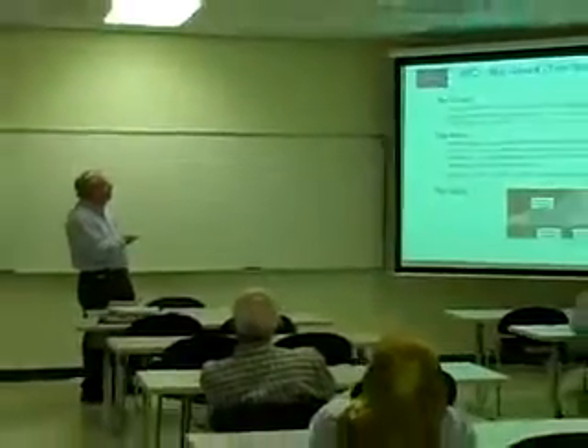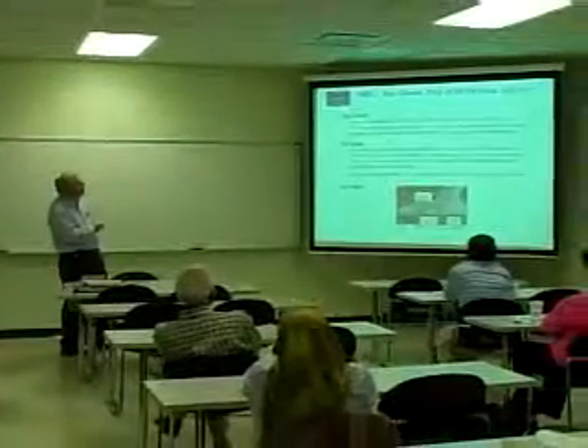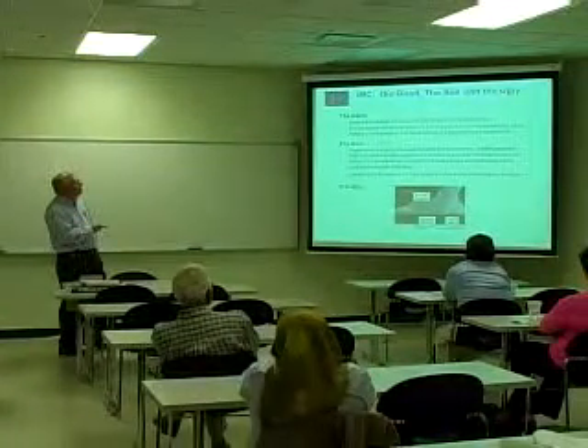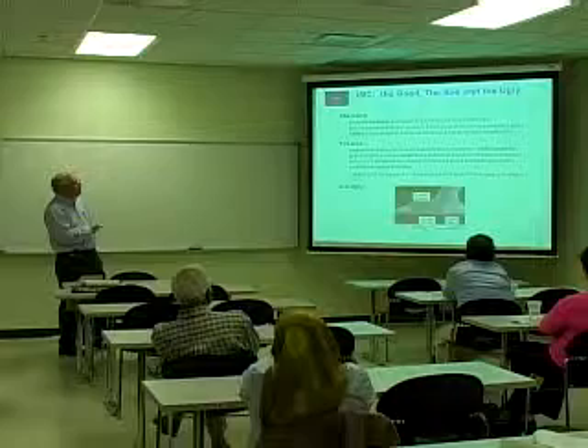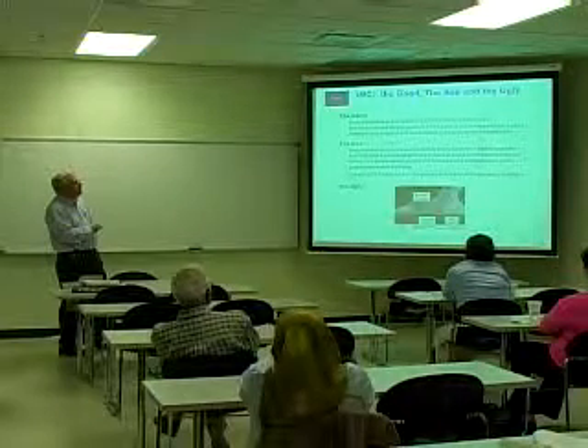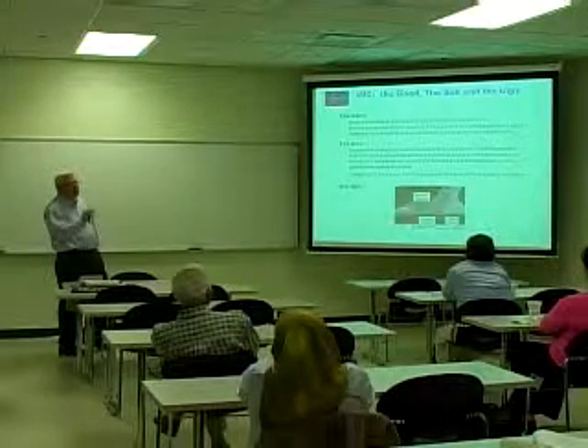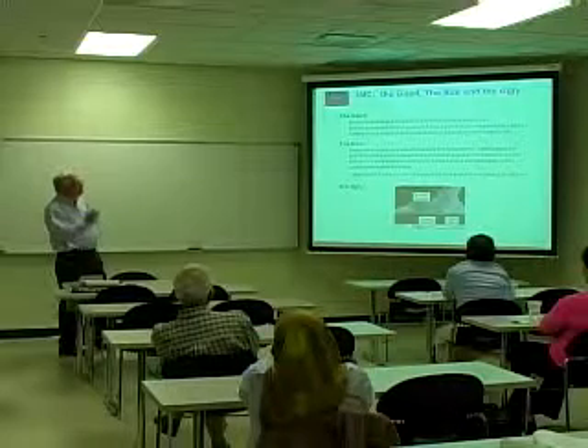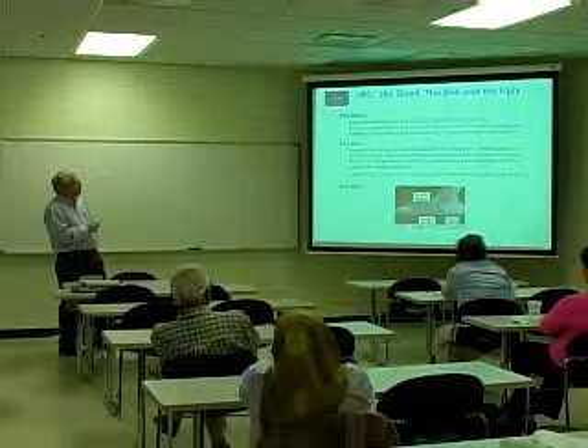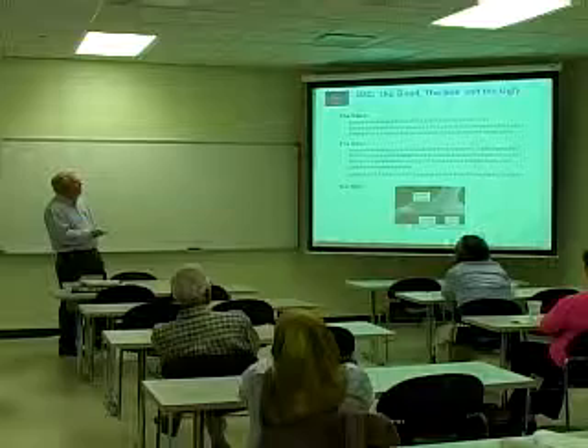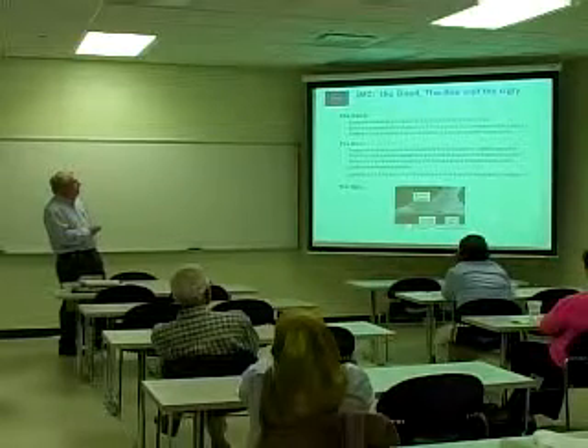And so what people do is they have to have some intermetallic formation. That's why I call this the good, the bad, and the ugly. You want some intermetallics, say typically tin on copper, to be around 1 to 2 microns of intermetallic. That gives good wetting, and it gives a reasonably good solder joint in terms of strength. If it's less than a micron, you probably get a relatively poor solder joint, poor wetting.